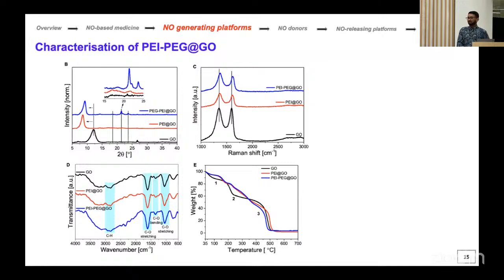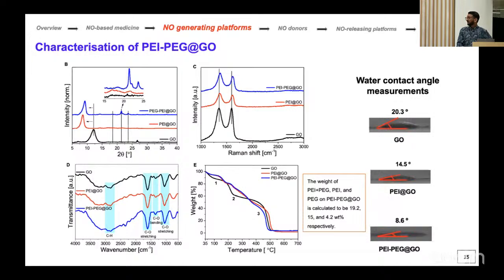I'm not going into the detail of XRD and Raman shift, but that's basically just to show the amine groups have been successfully conjugated with graphene. We also use polyethylene glycol because it improves the dispersibility of graphene, and it can also improve the retention time of these coatings in the circulation. And then TGA, just to show how much polyethylenimine and polyethylene glycol have been conjugated onto the surface of graphene, and then also water contact angle to show the improvement in dispersibility of graphene.